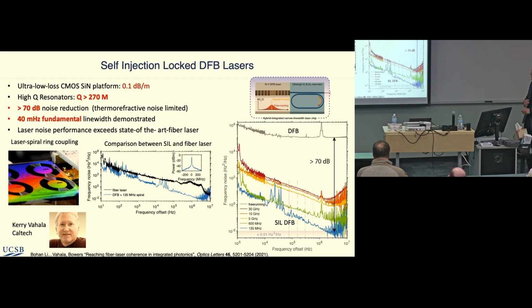So this compares the frequency noise in black of, I think, one of the best fiber lasers. Again, they're long cavities, they tend to be quiet lasers, we use them in the lab all the time. But these lasers are now almost 20 dB better at a megahertz because of this high Q silicon nitride cavity.